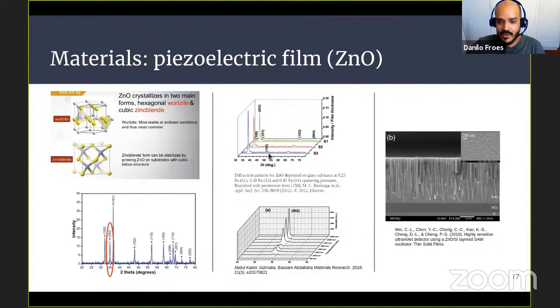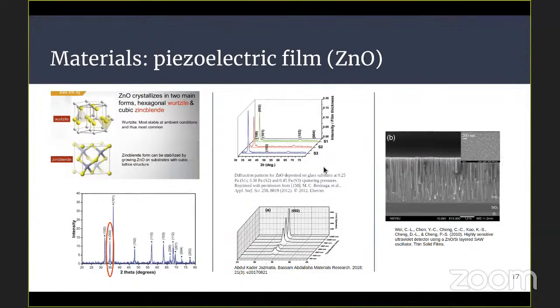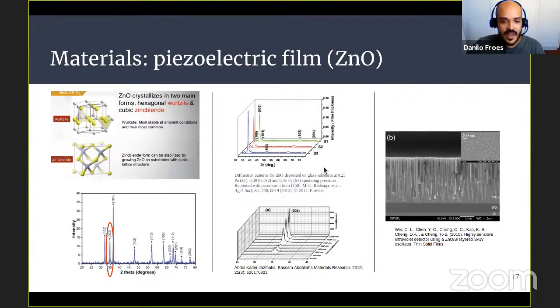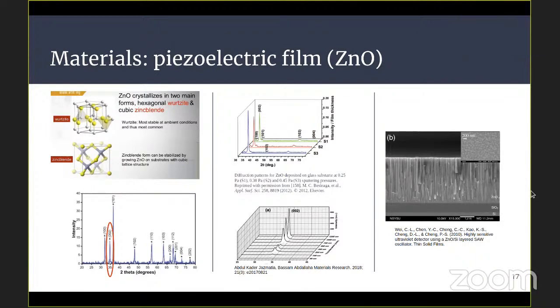By varying the film thickness, we needed a film in order to have this orientation. We need a high thickness, in the order of 1 micrometer, to have an effective piezoelectric effect. Here we need high thickness, we need oxygen, and the cross section of our material has to have these highly oriented grains. So this is what we're aiming for.